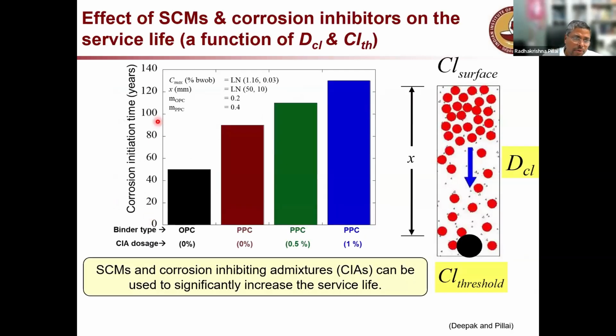So this is again corrosion initiation time. You can see the black one, it's here OPC with no inhibitors. Let's say you get about 50 years. This is a parametric study, so you don't look at the absolute value on the left side, but look at the percentage increase in the service life. So let's say you get 50 years in case 1, which is the controlled scenario. Now you put some fly ash in the concrete and no inhibitors. You will still get about 90 years of life, almost doubling the life, right? Now, if you put fly ash and a little bit of admixtures, you get a little bit more life. In the blue case also, you can see a little bit of fly ash and corrosion inhibiting admixtures, and there you get around 120 plus years of life.